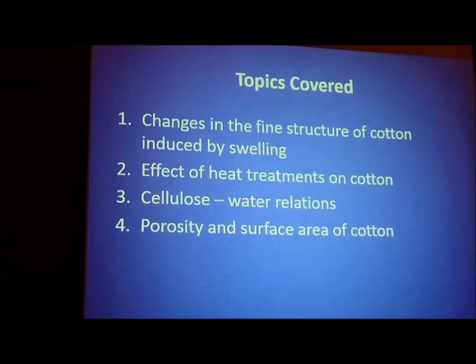I should clarify here that when I refer to mercerized products, I mean cotton fibers with a cellulose 1 crystal form that have been treated with a solution of an alkaline metal hydroxide of sufficient strength to cause essentially complete conversion of the lattice structure to the cellulose 2 form. First, I will discuss reduction in crystallinity of cotton cellulose by swelling.